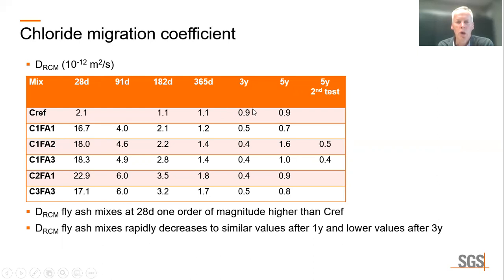But then, after 1 year, we see a rapid decrease of the migration coefficients to a comparable value as the reference concrete. And after 3 years, all fly ash mixes even show lower values.